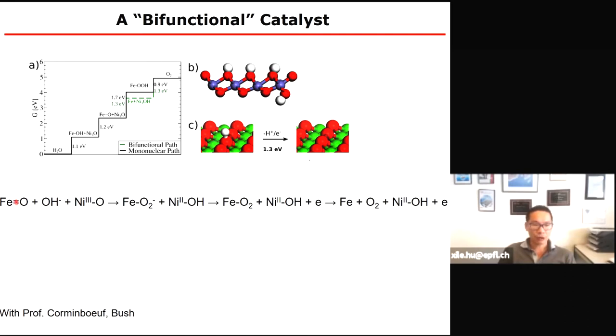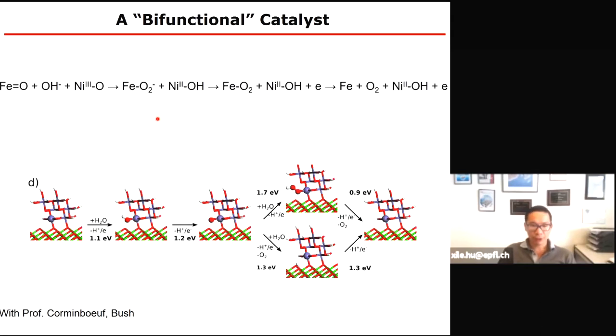We can see this more easily from this equation. So we have iron oxo species, hydroxy attack. This is difficult, but if hydrogen is simultaneously removed to a hydrogen atom acceptor to make a nickel 2 hydroxy, then we don't have to form iron OOH. So we get a low energy species, and through internal electron transfer, we can release O2, regenerate the iron active site, and have a nickel 2 site. Okay. Now the last step will be to regenerate the nickel 2 site into nickel 3, and we calculate this to have 1.3 eV. So overall, the whole energy barrier is lowered.